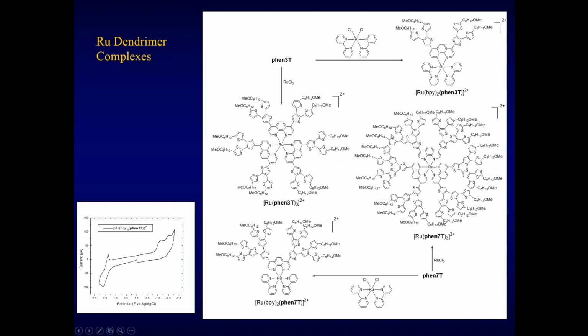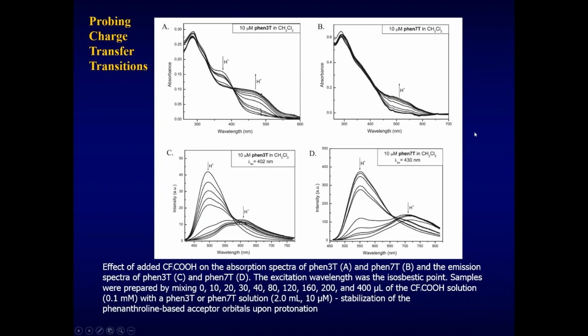In this case, a ruthenium complex with phenanthroline derivatives or bipyridine. Here we can see a complex of ruthenium forming a tris-bipyridine derivative as shown in this schematic diagram. So you first synthesize the dendrons, in this case the ligand, which can then be complexed with ruthenium, resulting in structures like this. And what's interesting is that we can have a full dendrimer or a half dendrimer.